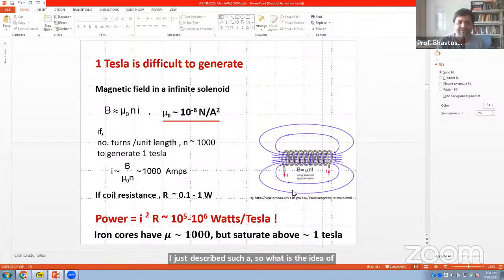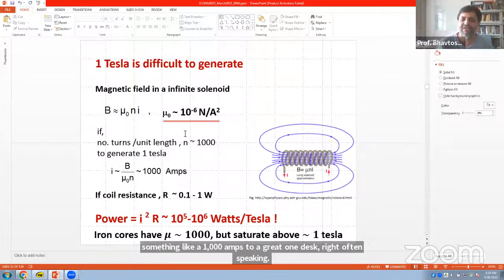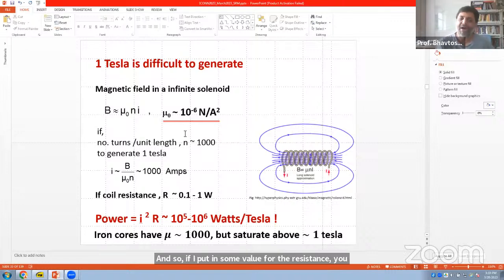One thing which one should note is that when we're talking about magnetic fields, 1 Tesla itself is a very large number, because the value of mu naught, the fundamental constant which is the permeability of vacuum, is so small that if I were to just make an iron solenoid or just a copper solenoid and drive some current through it, then using this formula, B is equal to mu naught N i, where N is the number of turns per unit length, because mu naught is so small, I would need something like 1000 amps to generate 1 Tesla, roughly speaking. And if I put in some value for the resistance, you can see that I'll need something like 100 kilowatts to a megawatt of power to generate 1 Tesla.